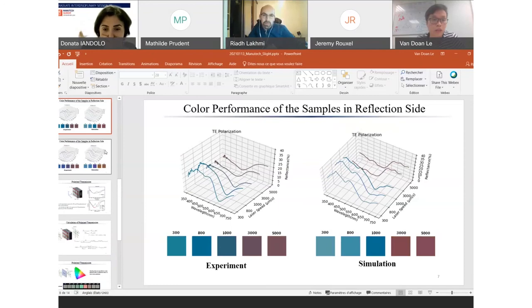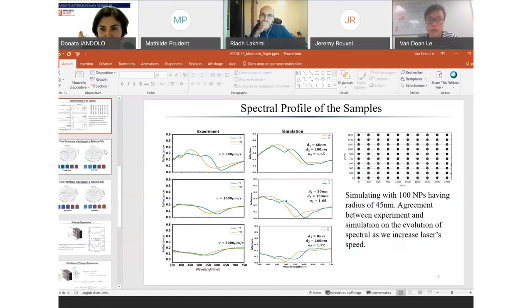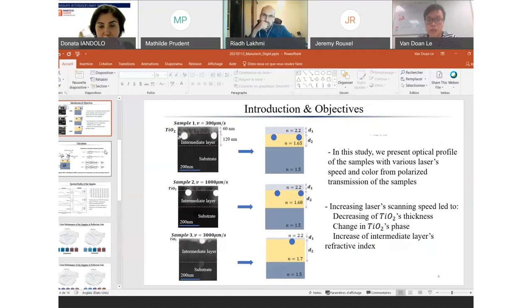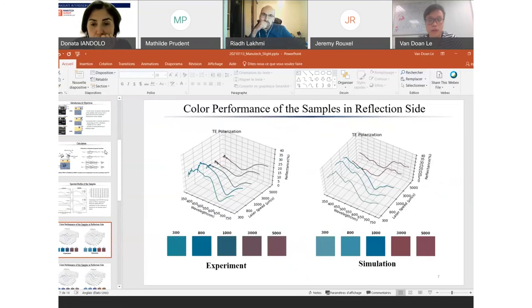Okay. So I would say that it is due to the optical property of the layer, the sample. In the sample I modeled here, I change the thickness and the refractive index, and the result from the simulation agrees quite well with the experiment. So I can conclude that there is no chemical change involved in my simulation, just purely optical. Okay, thank you. No problem.